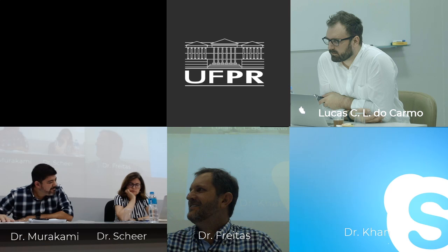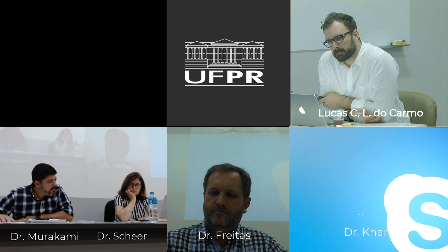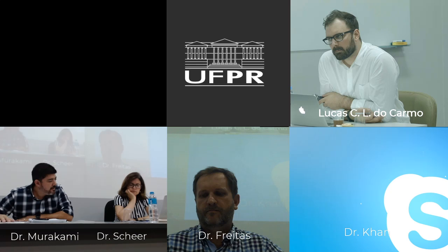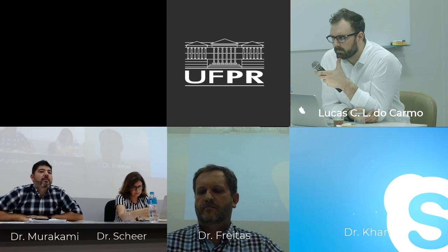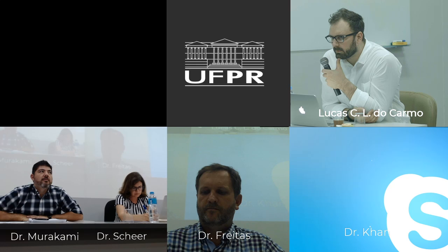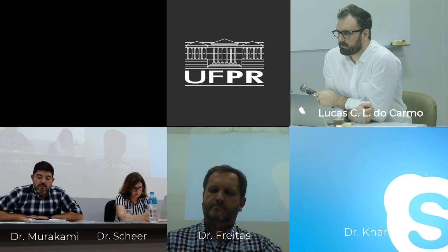What I'm saying is there is maybe a better way of getting more accurate yield stress data from your dynamic experiments. So what you could do is plot on the y-axis G prime times strain, from your stress data, versus strain, and then you'll see a maximum, and the maximum corresponds to yield. Okay, thank you. Just something for you to think about.